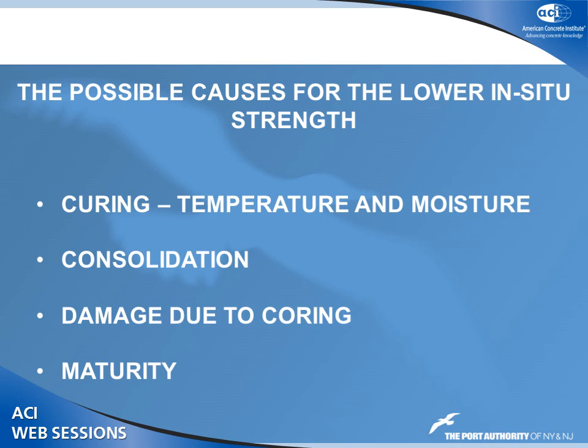Now, coring. Yeah, I guess you could damage it by coring. There's no doubt about that. I would certainly not debate that. Maturity, again, maturity could be an issue if it's during the winter. But other than the winter, I don't think maturity is ever the case, meaning that the maturity of the concrete in place is less than the cylinders. It's usually the other way around, that the maturity of the concrete in place far exceeds the 28, 56-day breaks that you have. That's never an issue.